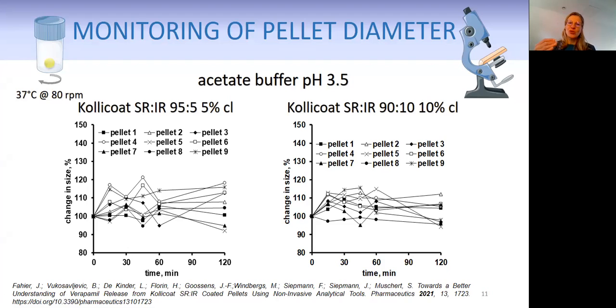Is it due to a water imbibe, where the water is going into the pellet core, the pellet core will swell. And then when the pellet core swells, we have a pressure on the coating. And this might actually cause rupture of the film coating. When we've got a rupture of the film coating, all drug will be released at once, which could actually explain some of the individual single pellet release curves.